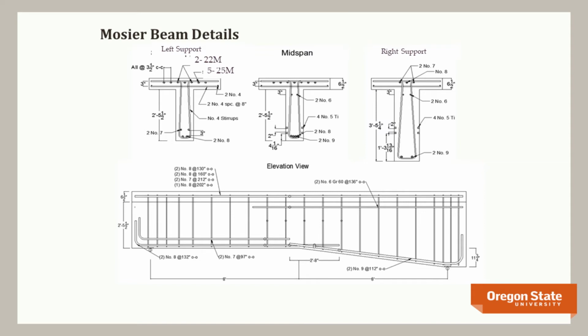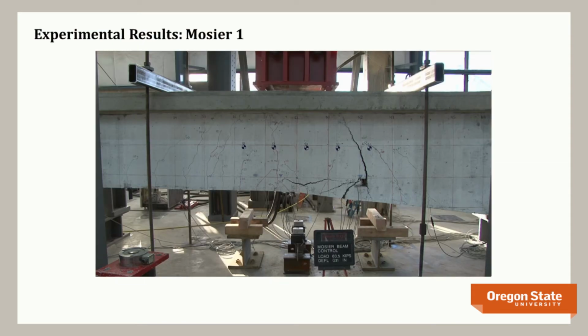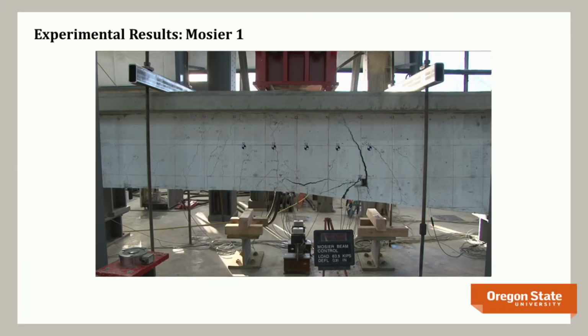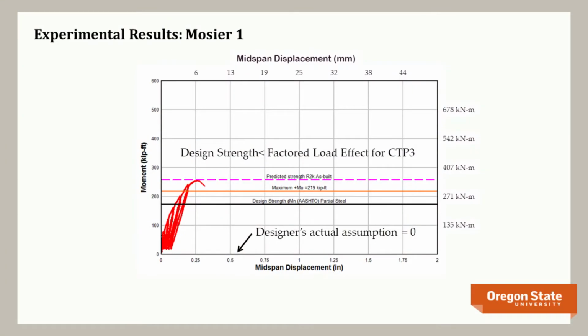This is a control specimen. Essentially, it's a very fast test. Because there's a negative moment for dead load, we actually produce the negative moment here when we do the repair, and then we apply the live load, which goes positive. So we're trying to simulate the real stress conditions as well. This is the start of the test, a little bit of cracking, done. All right, it's pretty quick. And in fact, the cracks that are produced are very much like the cracks observed in the field. Here's the load deformation response.